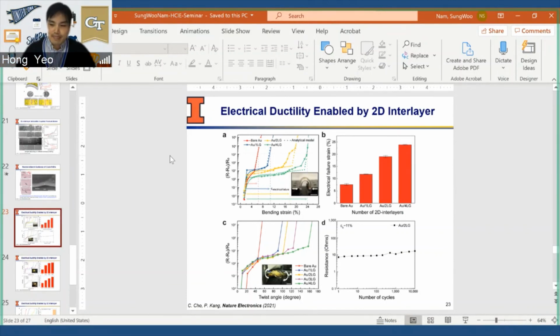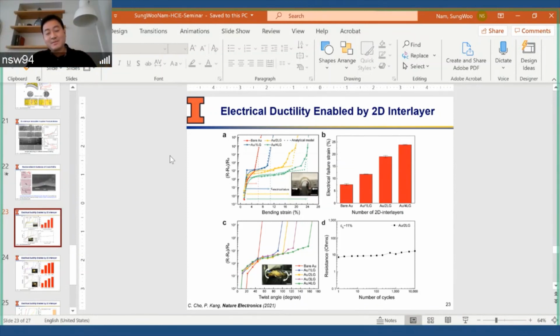That's a great question. Actually, we did that experiment. The simplest experiment we did was to put the Kirigami structure on PDMS or VHB, which is very sticky. When you put it on, the structure cannot buckle out of plane anymore. So if it's super sticky, you are only limited to in-plane, and that substantially reduces the stretchability.